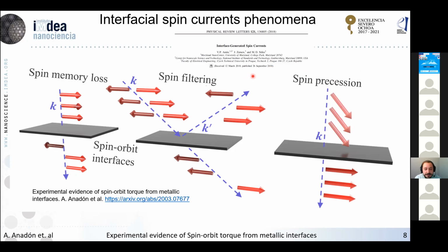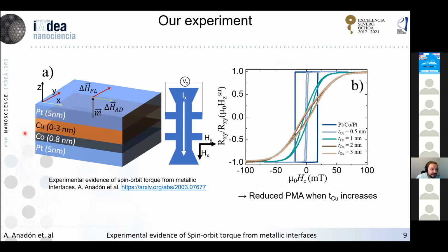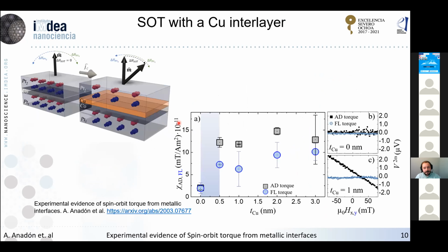So in this study, they suggest that a very interesting system to study this interfacial spin current is the platinum, copper, and copper cobalt interfaces. So what we came up with is, as I said at the beginning, we introduce a copper interlayer in a platinum cobalt platinum symmetric system. Then we take the samples and we make Hall bars patterned by optical lithography. And just by looking at the anomalous Hall resistance, we observed that the perpendicular magnetic anisotropy of the system decreased slowly when the copper thickness increases, but the samples are still perpendicularly magnetized up to 3 nanometers of copper.